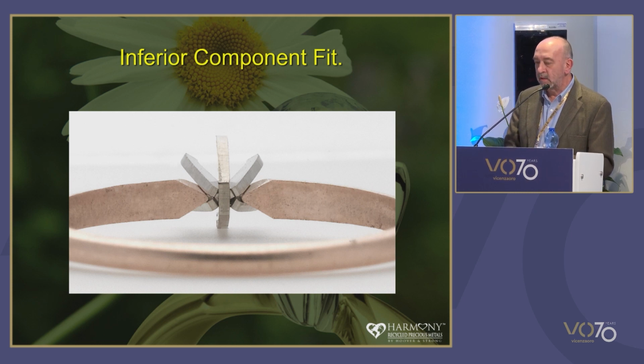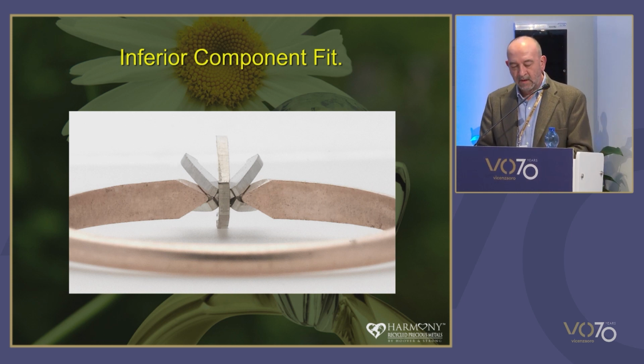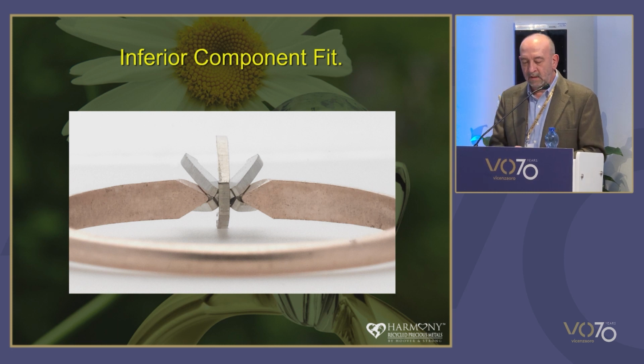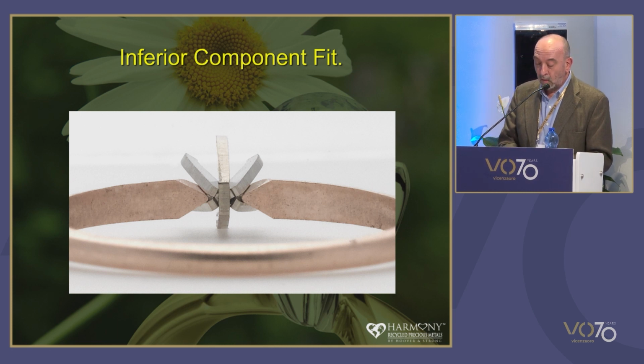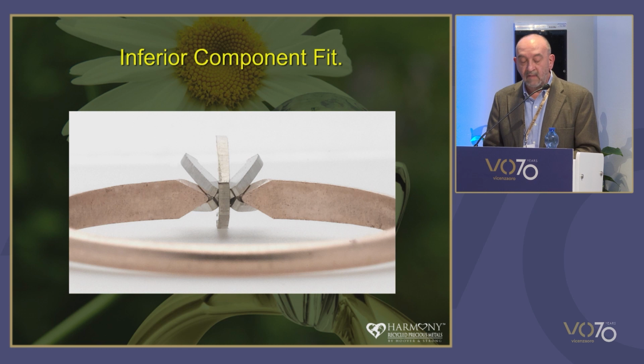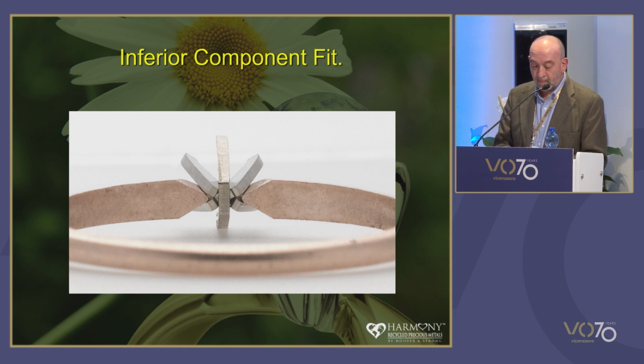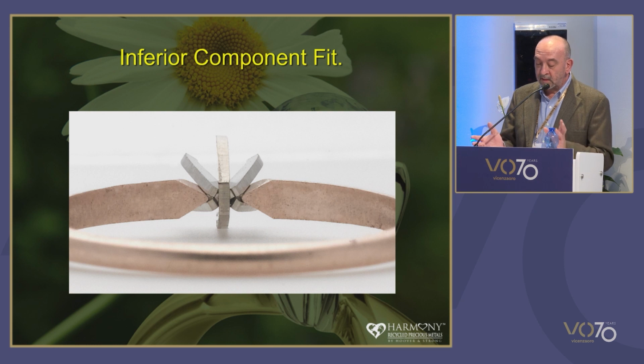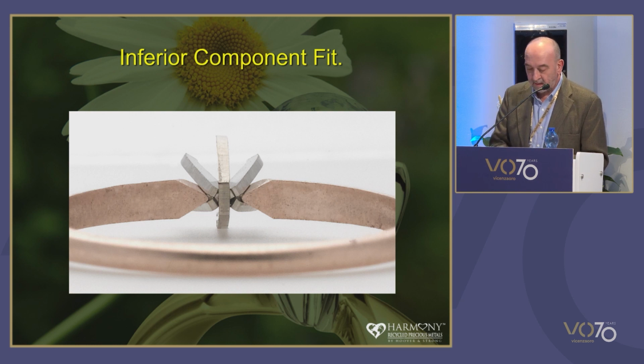So we analysed the production process and we found out that the assembly department had started to pre-finish all the components before they assembled them. It saved them time during their production process, but unfortunately, the effect was to round off all the sharp edges, making the overall fit of the components inferior, as you can see from this last picture here, large gaps. It resulted in the presence of these big voids, and so the solder was acting as a filler, not just a joiner.